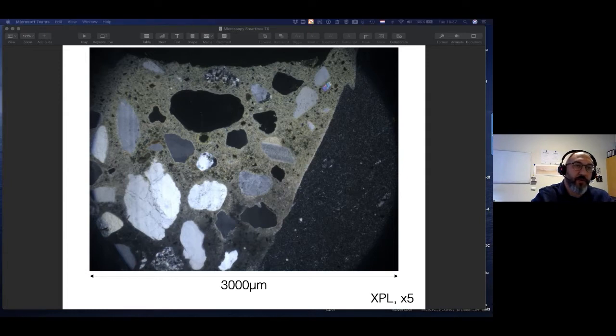So it penetrates in your concrete, and all your non-carbonated cement paste turns into this bright birefringence in cross-polarized light. Don't forget. Why? Because of the generation of calcium carbonate crystals, probably calcite or other polymorphs. And we observed them in this color because of its birefringence.